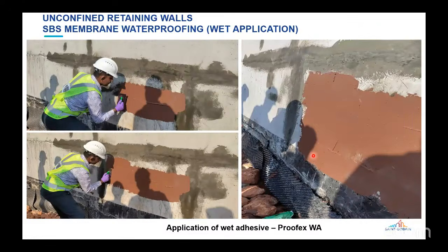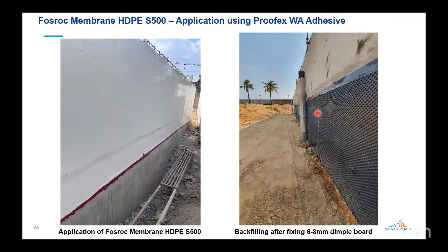So here we have an adhesive which is used, for example, if you have a substrate which is wet or damp. So there is a special adhesive which, for example, if you want to do a waterproofing application immediately after rain, there is a special adhesive available with which you'll be able to apply the waterproofing material even if the concrete surface has got high residual moisture. So some more applications of this product.